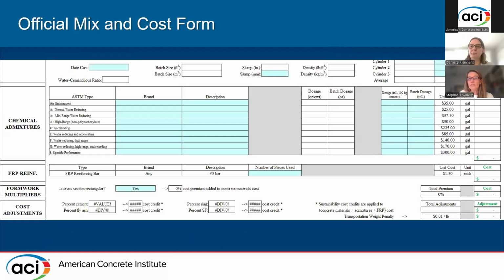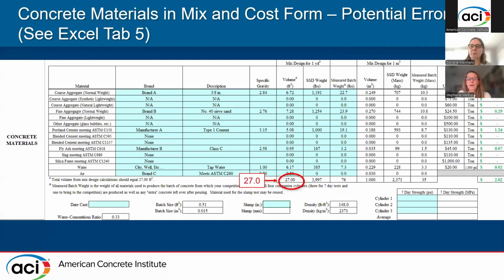Densities also have ranges that are permitted. So here is an example of the volume totaling up for the mix design for 1 cubic yard. We can see that the volume totals to 27.00 cubic feet. That is equivalent to 1 cubic yard. We also see that the volume and the saturated surface dry weights are used to calculate density in your spreadsheet.